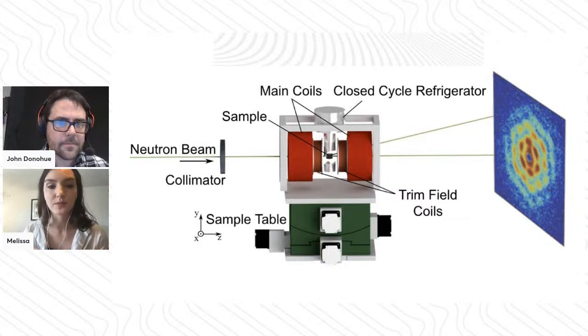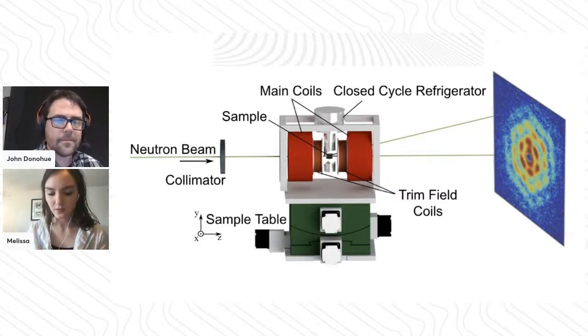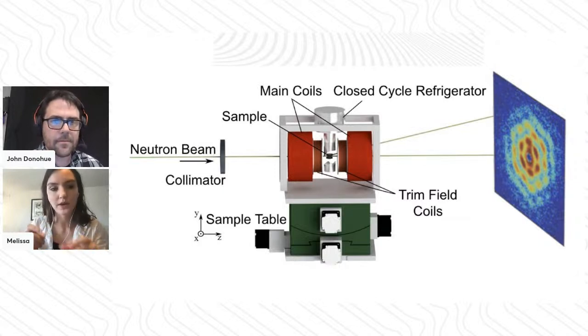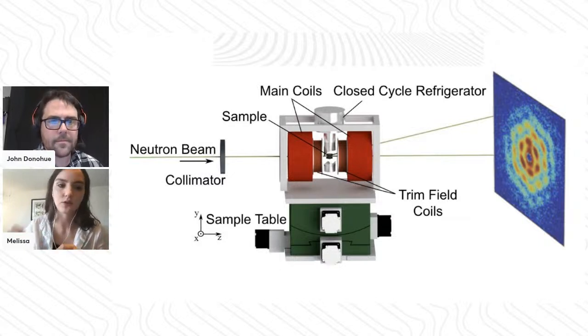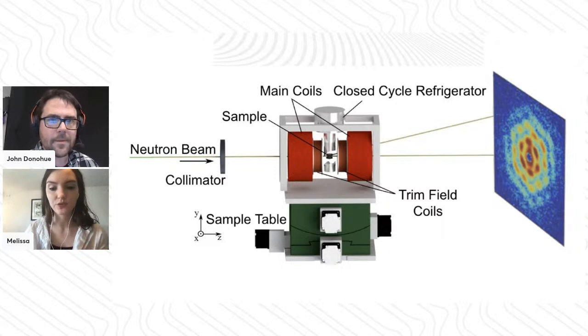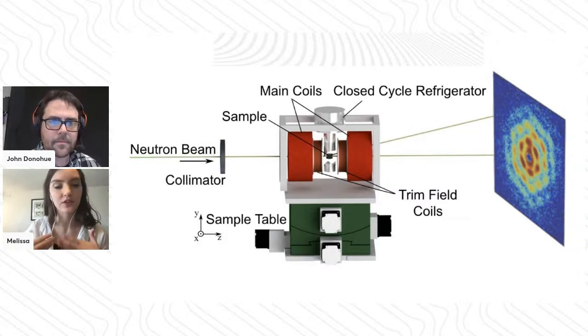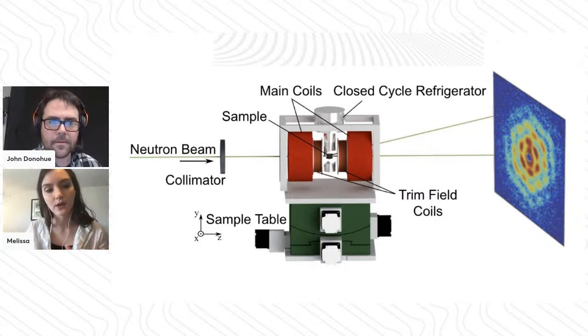There's a bunch of different ways in which disorder can arise. You can think of disorder in terms of crystal, like polycrystalline disorder - you can have different crystalline domains in your material. You can also have just disorder inherent to the growth process. Whenever you're growing material, it's never going to be perfectly defect-free. There's always going to be some sort of vacancy, maybe some impurity. But in the case of this material, its composition is inherently site disordered.